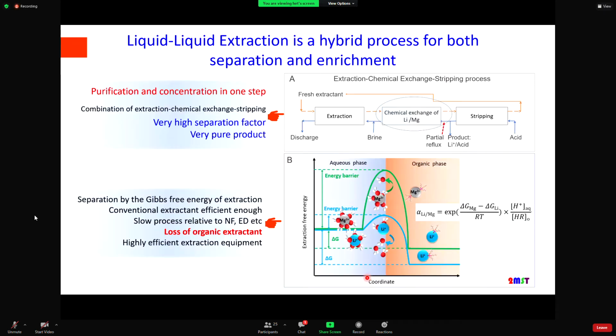How does liquid extraction work for magnesium-lithium separation, or lithium extraction? This figure shows that liquid extraction basically consists of 3 steps: the first is extraction, then chemical exchange of lithium and magnesium, and finally stripping. Every step has a separation capacity as well as enrichment capability, so we can achieve a very high separation factor and a very pure product.